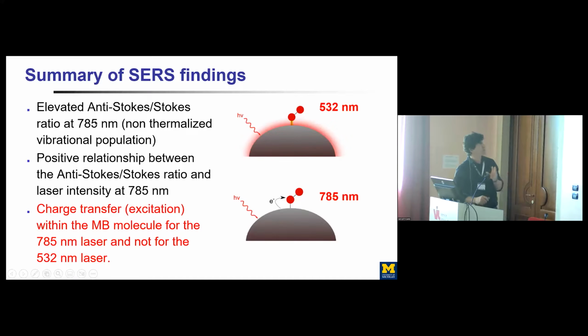Just to summarize these surface enhanced Raman spectroscopy measurements, what we see is that there's an elevated anti-Stokes to Stokes ratio at 785, basically communicating to us that we have a non-thermalized vibrational population. We have a positive relationship between the anti-Stokes to Stokes ratio and laser intensity, again at 785 and not at 532. So what this is telling us is that the charge transfer within the methylene blue molecule for the 785 laser is observed in these measurements and not for the 532 laser.